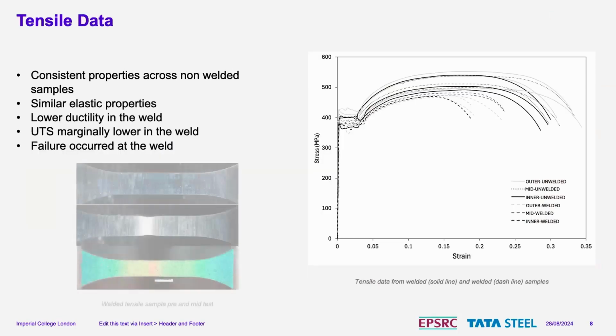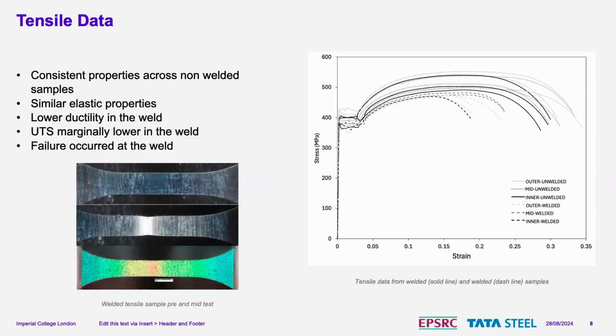And so the outer surfaces do seem to exhibit less ductility than the middle of the sample. If I then show you the welded samples themselves, we've got the weld running this way through them. You can see before test and during test, and this is my DIC that you can see. We've got two bands down each side of the weld, and in each of these welded samples, we do get failure at the weld.